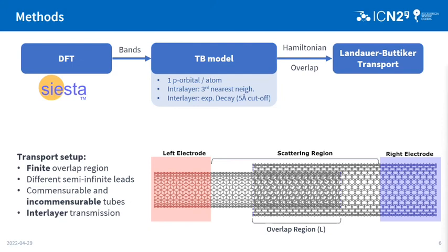This has already been done for graphene, and it gives accurate results for the band structure, but an interpretation of the individual parameters becomes a little bit tricky because there are repulsive and non-repulsive terms, and some have actually argued that from the perspective of analyzing the tight binding model, it does not make sense to go to third nearest neighbor because the meaning is basically completely lost. It's just a fitting parameter.